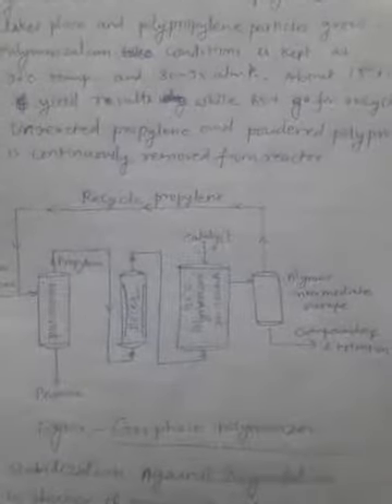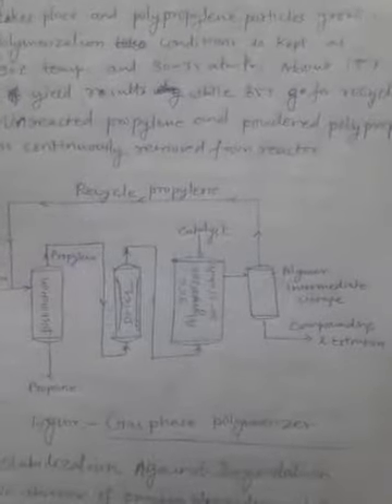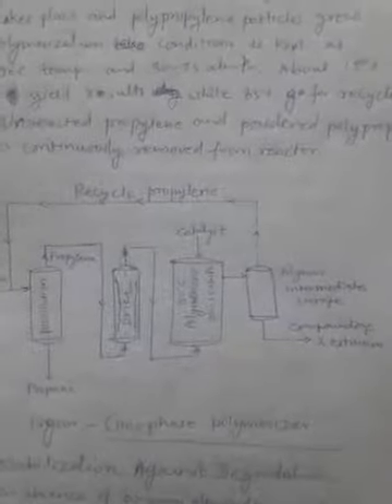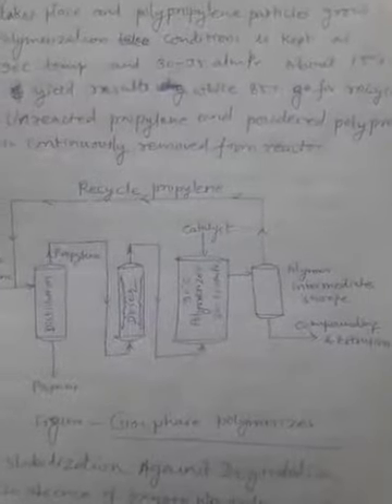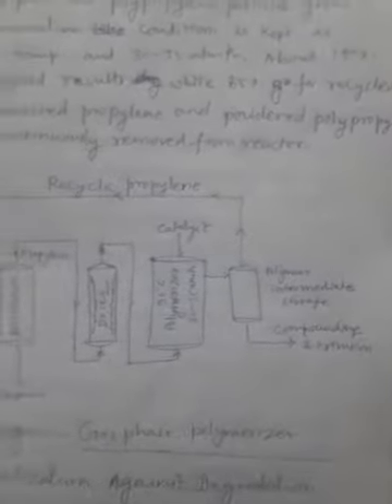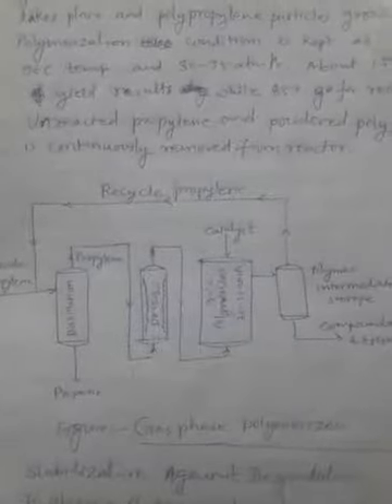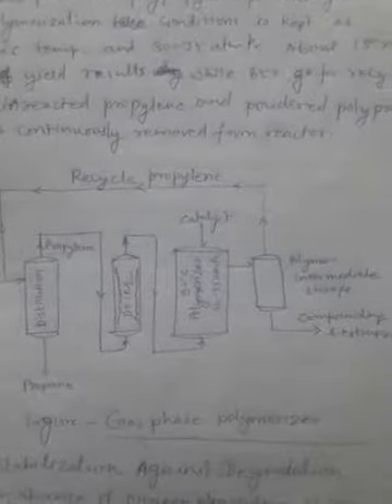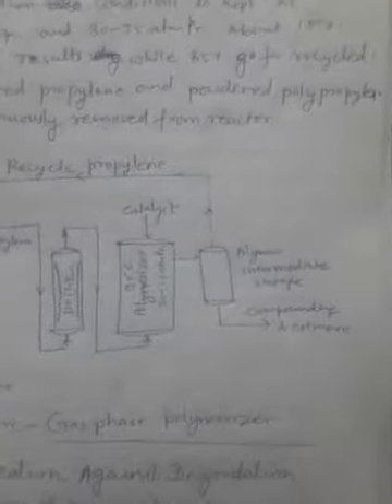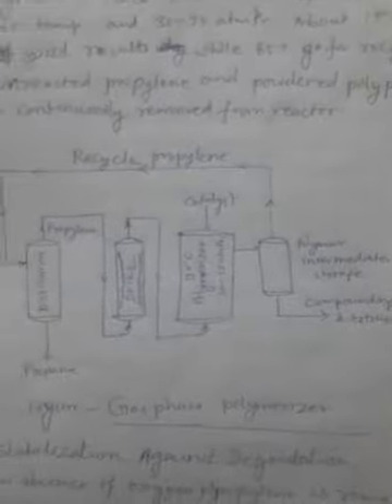During this polymerization, out of the total propylene gas, 15% gets converted, or you can say a 15% polymer yield results, while the rest, 85%, goes for recycling as unreacted propylene gas, and finally the polypropylene powder is continuously removed from the reactor. You can also see the diagram here.